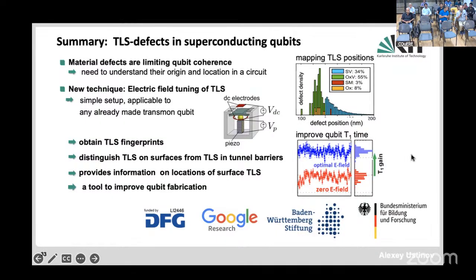Is there some limit on this T1 which one can achieve because of these defects? Is there something which, like this coherence time T1, we cannot go beyond, say, 100 microseconds or 150 microseconds? Nowadays, in particular at IBM, they are working with devices which have T1 on the order of a millisecond. Could be a fraction of a millisecond, could be a bit larger. But as I already mentioned, this T1 is not always a metric because it fluctuates as a function of time. But the best devices show T1s, and actually T2 comparable, in the range of a fraction of a millisecond, up to maybe a bit more than a millisecond. More recently, there was a PRL paper from Princeton published this spring, showing that one can achieve coherence times over a millisecond by passivating the surface of a superconductor by gold. That's very recent work.